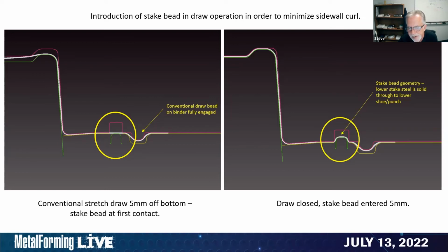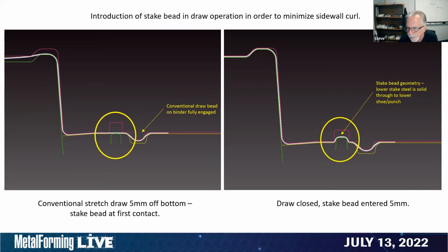That would be a detail that's through the lower binder and mounted solid to the lower shoe or lower punch. And then on the right, that's the die closed. The stake bead has finished entering. In this instance, it's 5 millimeters, but that 5 millimeter introduction of the stake bead at the bottom of the stroke performs a last minute tug on this vertical wall as it's being formed in the draw. So if we go to the next slide.